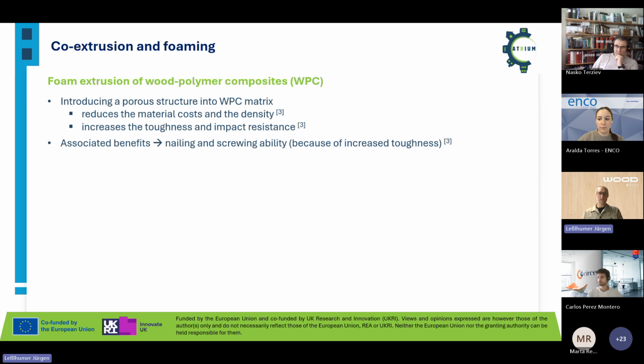And some words on the foam extrusion of WPC, so these wood polymer composites. So we introduce a porous structure into the WPC matrix, and that has the big advantage that we can reduce the material costs through the density reduction, and on the other hand, we need less material. And through this foam structure, we can increase the toughness and also the impact resistance. And that helps us, for example, that we can do nailing and screwing. So that's also a big advantage and necessary for this WPC terrace decking we are developing within the ATRIUM project.